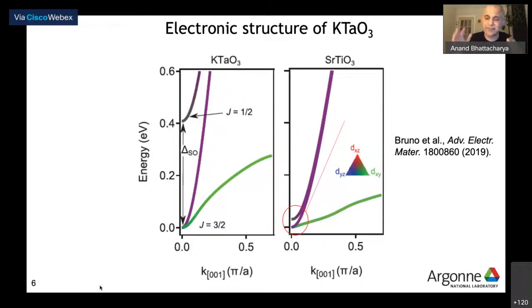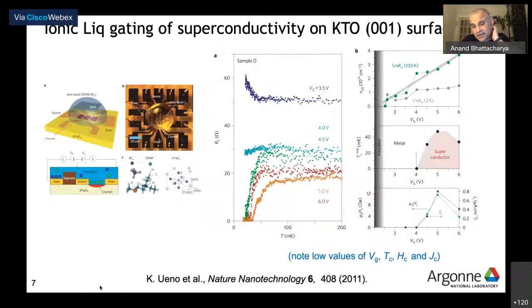so this is very nice. And so if you're interested in spintronics like I am and many others are, you might be very interested in looking at the system because you have this very high spin orbit coupling that perhaps you can play with. All right. So the really surprising thing to many some years ago was that actually when you take a single crystal of KTO and you gate it by using ionic liquid, what you get is a conducting electron gas at the surface. And if you choose the right conditions and cool it down to low temperatures, you see superconductivity at about 47 millikelvin TC, the highest value that they reported.